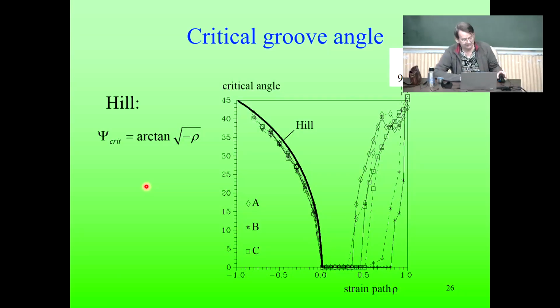On the left part of the FLD, the critical groove angle is simply arctangent of the square root of minus rho. This is the Hill solution. He also suggested that for the positive part, it is 0. So the minimum strain you get when the groove angle is 0.